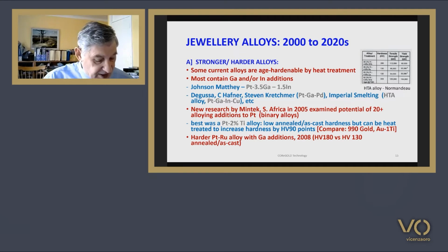Research carried out at Mintek in South Africa in 2005 has examined potential platinum alloy systems to identify suitable binary alloy systems that can be substantially age hardened. Over 20 alloying metals were studied in the preliminary trials at addition levels of 2 to 4%. From this work, the best alloy was a platinum 2% titanium alloy, which had an as-cast and annealed hardness sufficiently low to be easily worked and formed, but with subsequent heat treatment, the hardness value could be increased by about 90 figures.